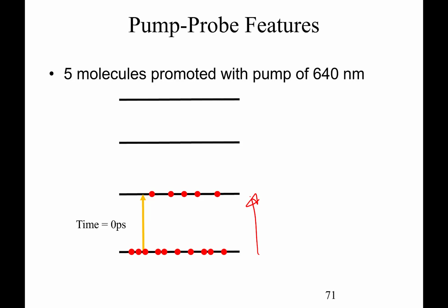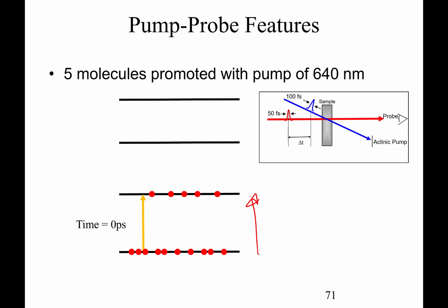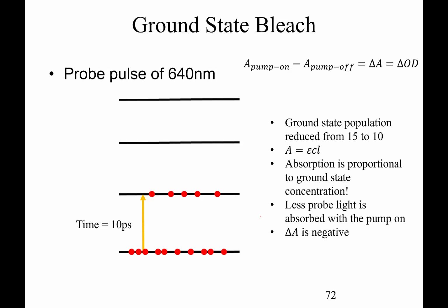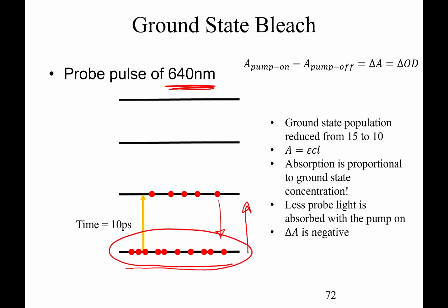Now the next thing that can happen is we've got this pump in here. This is the blue line that you're going to see in here, and what happens is we come through with a probe. We come in through with another pulse that arrives slightly later than the first pulse. So what happens now is, if that probe pulse comes in at exactly the same wavelength, it turns out that some of these molecules can get pushed upwards, and some of these molecules actually through stimulated emission can actually drop back down. So the other thing we might see is because the ground state in here is depleted, so there are fewer molecules in this ground state, what we find is that the absorption actually goes down because there are fewer molecules in that ground state to absorb.